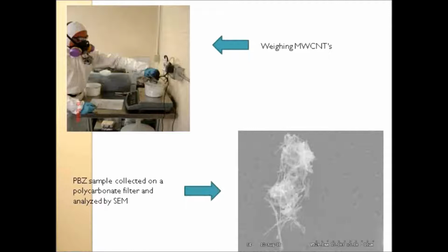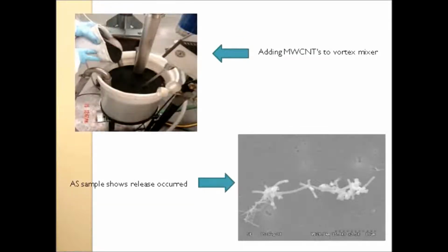Now here we did a little bit different sampling technique as far as analysis. We used SEM instead of TEM, and lo and behold, we're seeing these kind of structures now entering the breathing zone. Okay. So after he weighs it, here's another example where a potential for a release could occur. He's dumping it into a mixing vessel that's a rotary mixer, and we're sampling here at the edge of the rim of the bucket, and lo and behold, we're seeing material going from here and actually cascading over the top, or possibly rebounding off the surface of the liquid, becoming airborne and being captured by these filters.